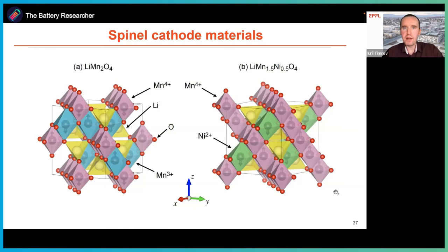We also consider other classes of materials such as spinel. So here I show two materials, lithium Mn2O4, and the second case where we partially substitute manganese by nickel. So in the left case, we have two types of manganese, manganese 3 plus and manganese 4 plus. When we fully remove lithium, manganese 3 plus oxidizes to 4 plus. While on the right hand side, we have manganese 4 plus and nickel 2 plus. So when we remove lithium, manganese stays manganese 4 plus, while nickel changes its oxidation state from 2 plus to 4 plus.